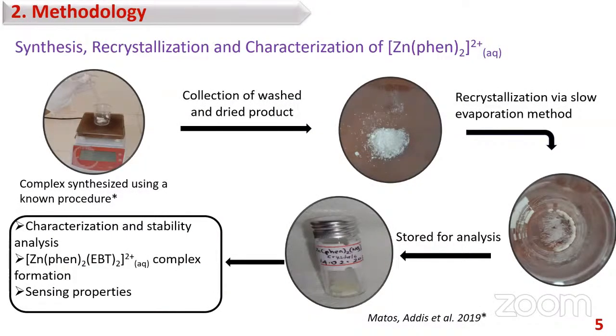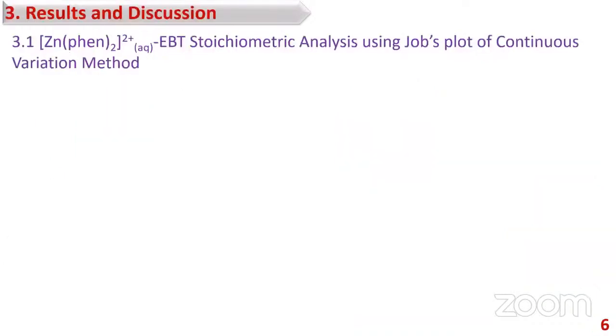The zinc phenanthroline complex was synthesized using a known procedure, and the washed product was collected and dried over a vacuum. Then, to increase the purity, the complex was recrystallized through the slow evaporation method and stored for further analysis. To confirm the purity and the complex formation, some characterization and stability analyses were carried out. In addition to that, zinc phenanthroline EBT complex formation and its sensing properties were analyzed.